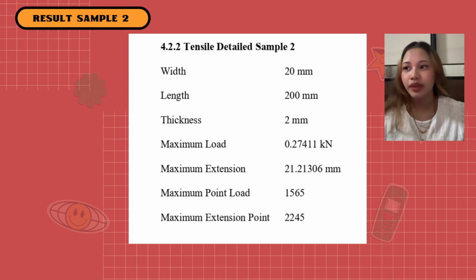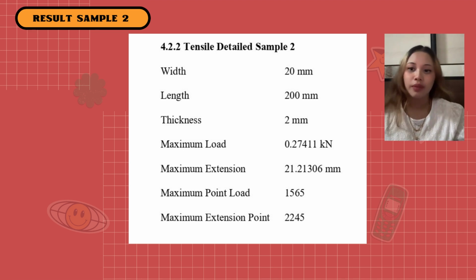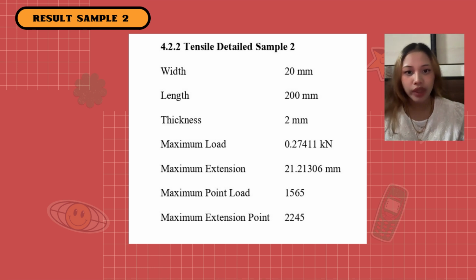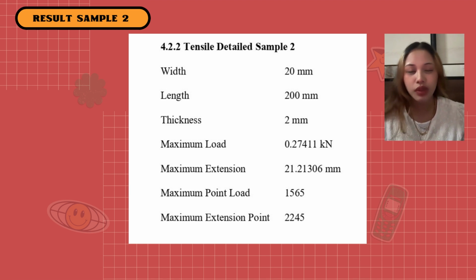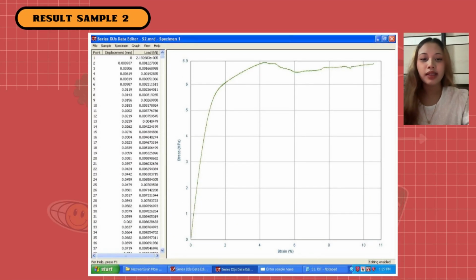The next one, we proceed with result for sample number 2, and this is the detail. Width, length and thickness are the same as sample number 1, which is 20 millimeter for width, 200 millimeter for length, and 2 millimeter for thickness. For maximum load 0.27411 kilonewton. Maximum extension 21.21306 millimeter. Maximum point load 1565, and then the last one is maximum extension point, which is 2245. And then this is the graph for result sample number 2. The maximum load is 0.27411 kilonewton.